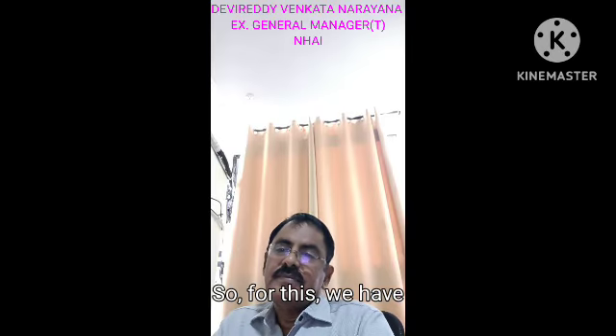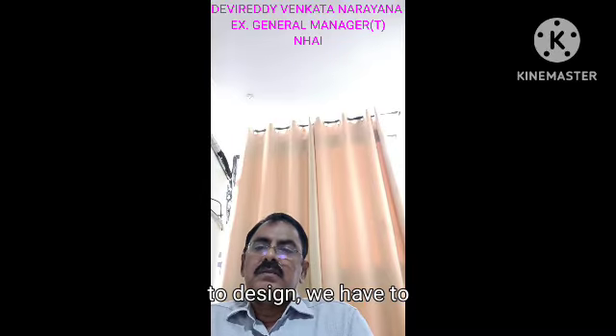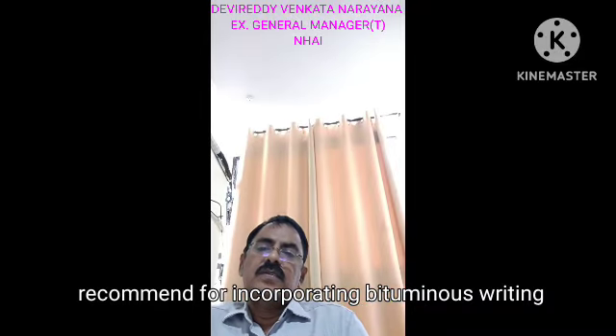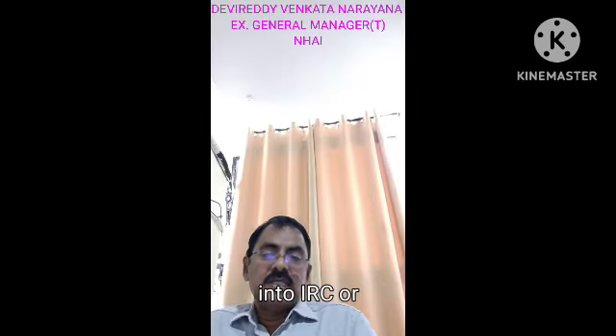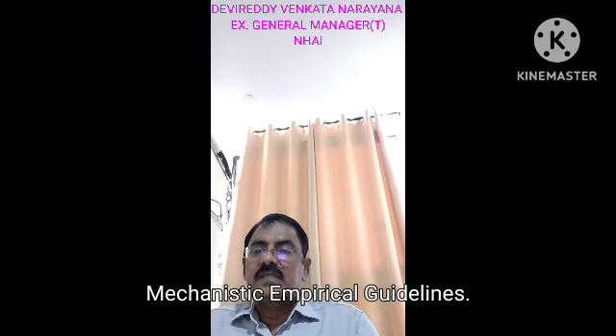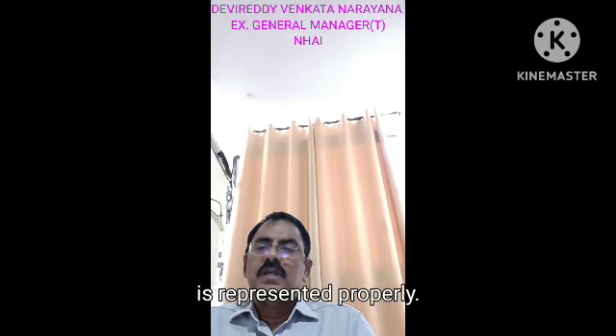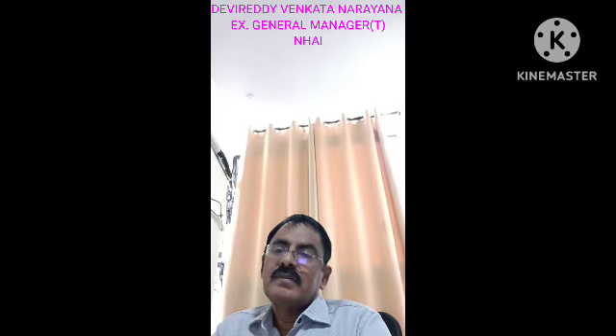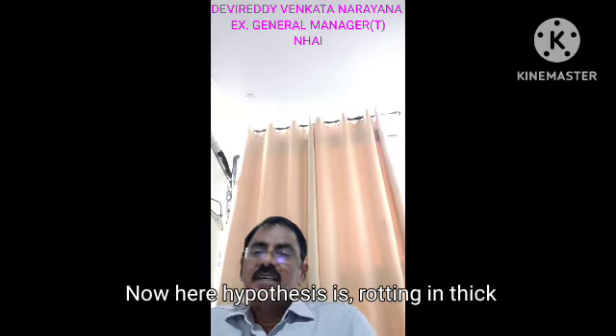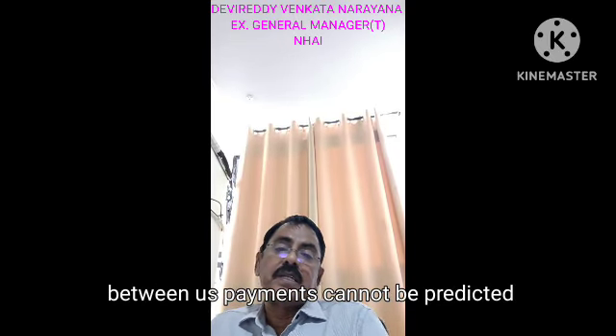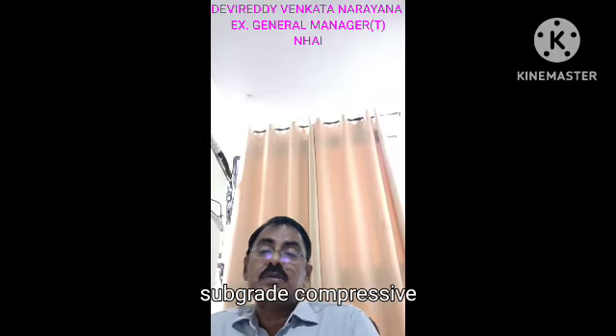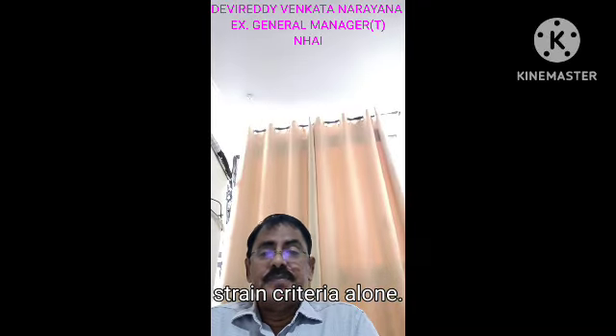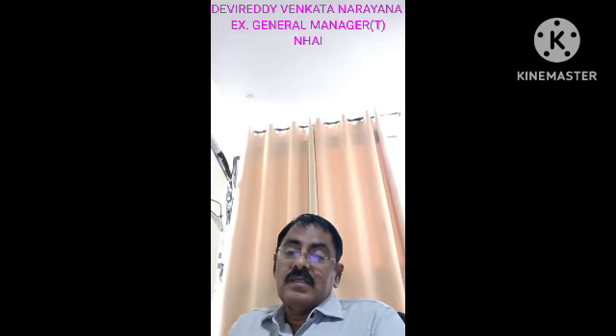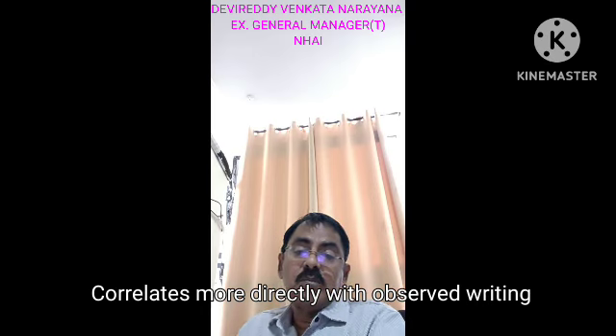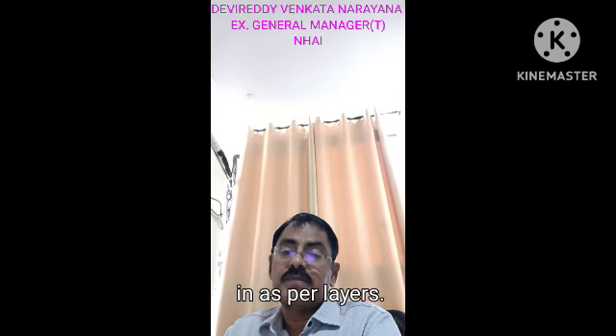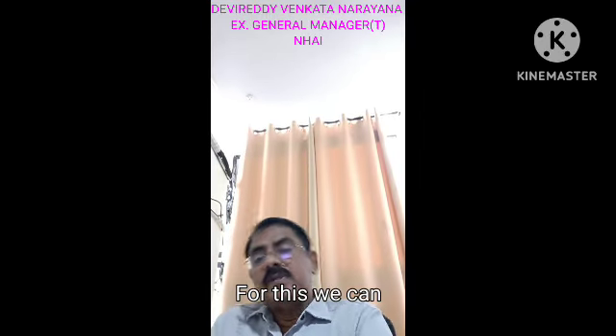So for this, we have to recommend incorporating bituminous rutting into IRC or mechanistic empirical guidelines. Then only this problem is represented properly. Now here the hypothesis is that rutting in thick bituminous pavements cannot be predicted reliably by subgrade compressive strain criteria alone. A mechanistic parameter correlates more directly with observed rutting in asphalt layers. For this, we can develop some methodology.